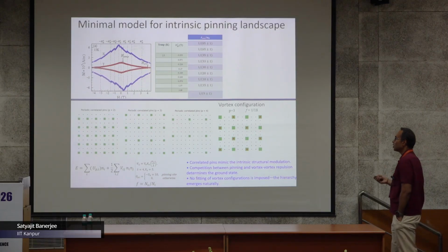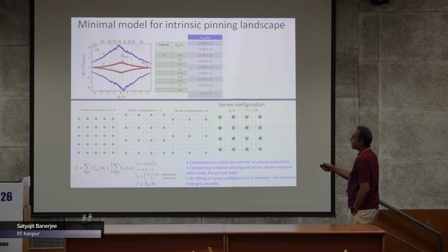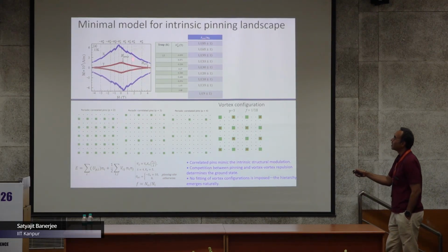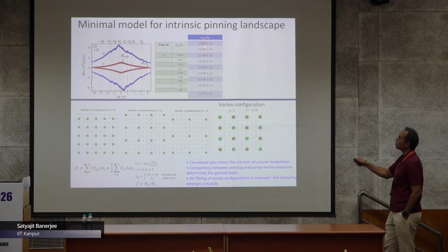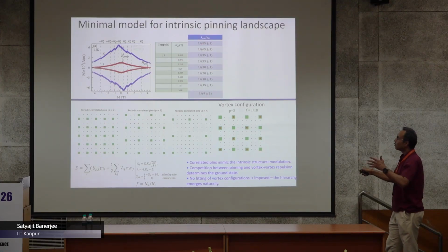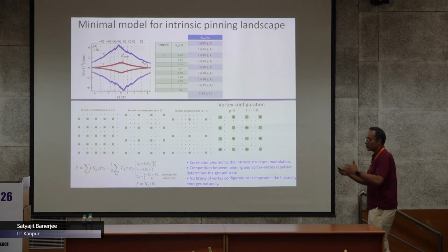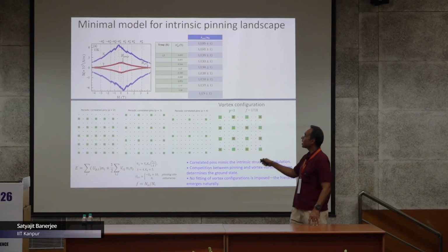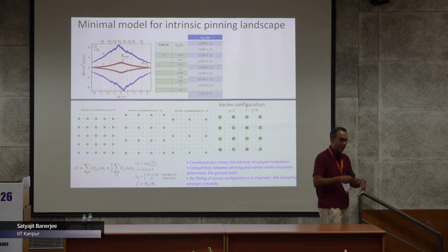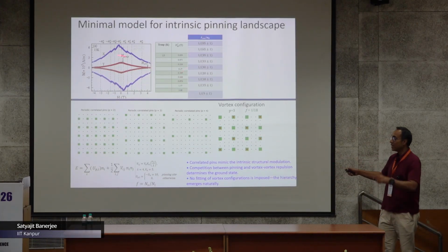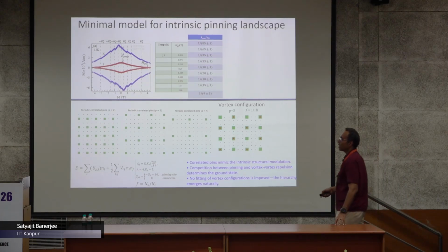We did an analysis of these values, and they correspond to a hierarchy of fractional filling. Each of these steps actually corresponds to 1 by 9, 1 by 15, 1 by 18, 1 by 20. So you can have a hierarchy of filling fractions populating the intrinsic periodic pinning landscape.